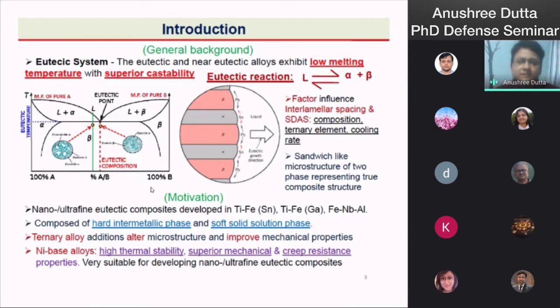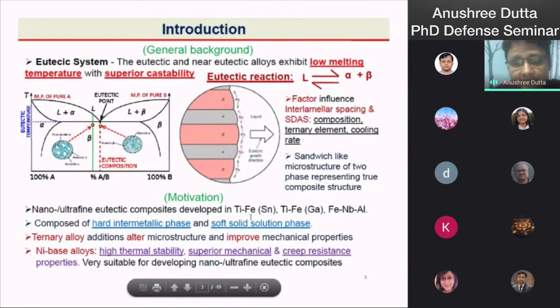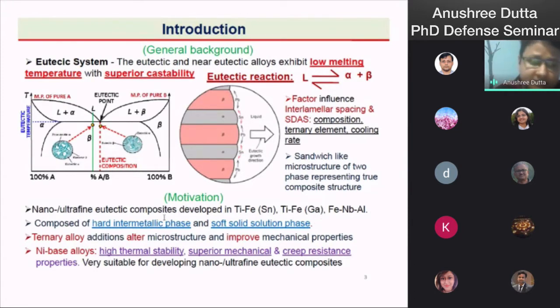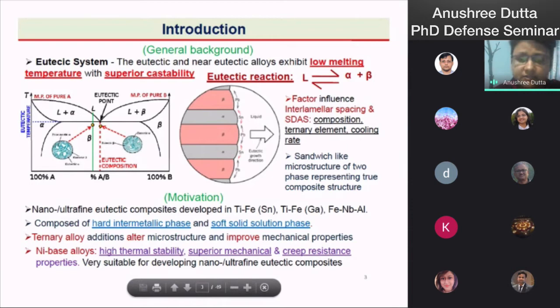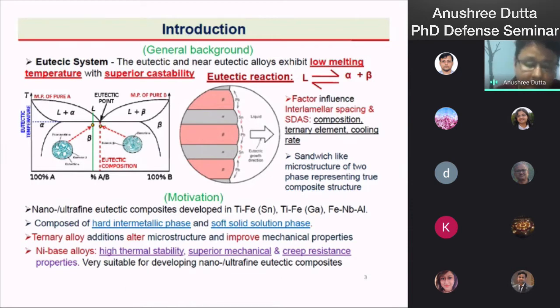The motivation of my work: nano ultrafine eutectic composites have been developed in titanium-iron, tin-titanium-iron, gallium-iron, and niobium alloy systems, which are composed of a hard intermetallic phase and a soft solid solution phase. These alloys exhibited superior mechanical properties, and a ternary alloying element was observed to alter the microstructure and improve the mechanical properties. Nickel-based alloys possess high thermal stability, superior mechanical properties and heat resistance. Therefore, nickel-based alloys are very suitable for developing nano ultrafine eutectic composites.